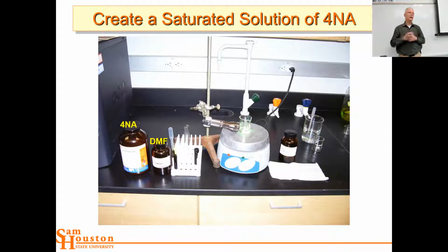So whenever you're growing crystals, maybe you don't know this, there's a battle going on between nucleation, so new crystals starting, and growth. So a molecule that's in solution can go to a new crystal, or it can go to an old crystal. If it goes to an old crystal, you have growth. If it goes to a new crystal, you have nucleation. And so there are these competing rates. And you can do different things to try to tailor one versus the other.